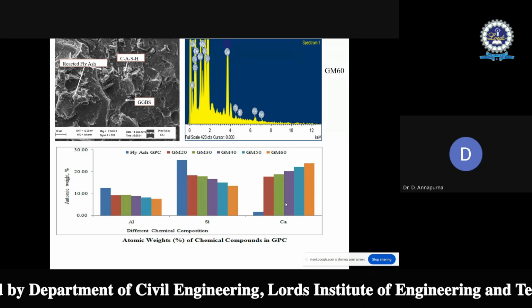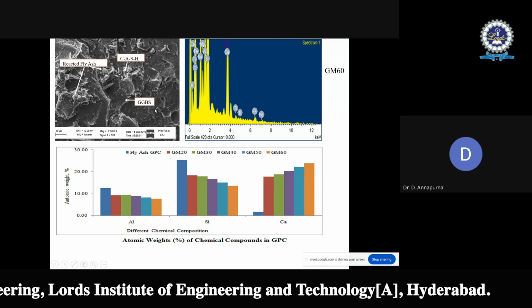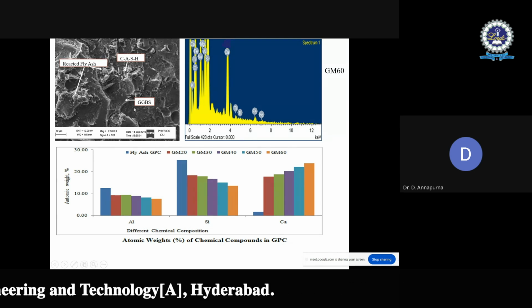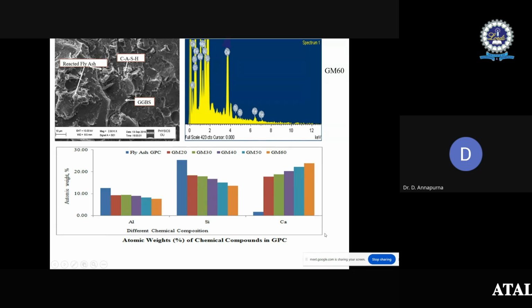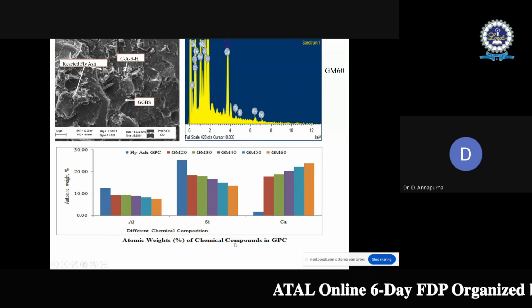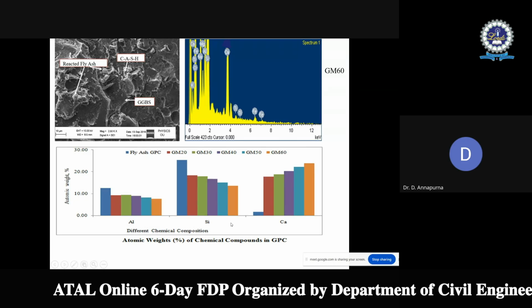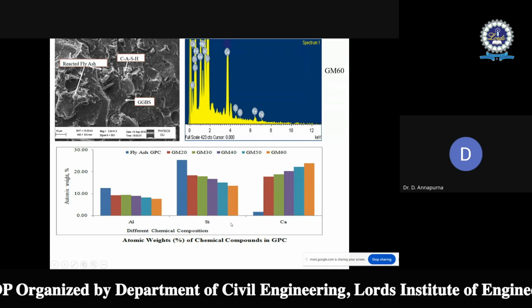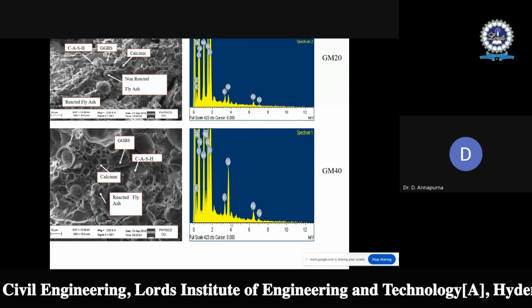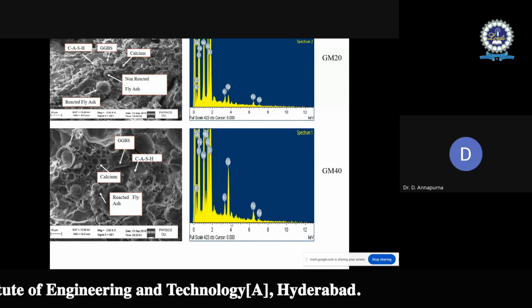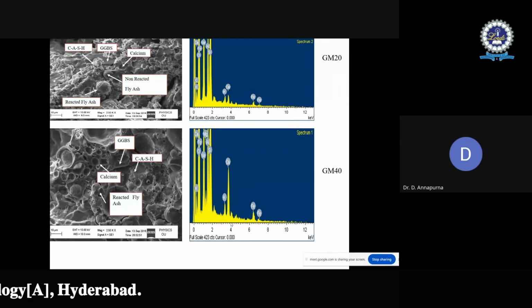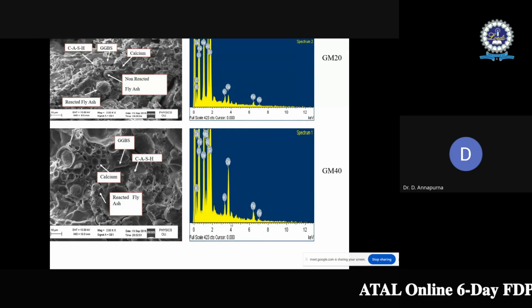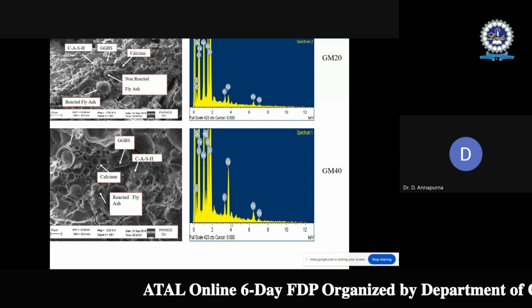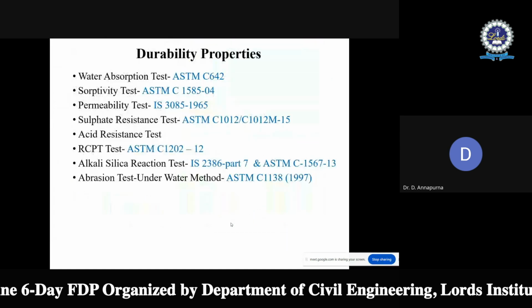Increasing the calcium content through the addition of GGBS causes a more compact and finer microstructure. If you look here, a more compact and finer microstructure is observed because the calcium is acting as a seeding or precipitating element. So from this, it is clearly seen that the addition of GGBS improves the microstructure. It makes the microstructure of geopolymer concrete compact. At the same time, it improves the setting action. So the compressive strength of geopolymer concrete is increased with the addition of GGBS.